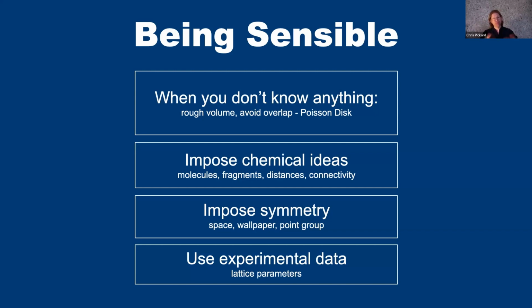Now that's sort of physics. But beyond that, you can also make the structures sensible from a chemical point of view, so that atoms are combined in fragments or into molecules, and the distances between the atoms are chemically sensible distances as well. So you can use this as a pre-filter for your random structures to just sample the ones that are likely to be low energy. Now, this is biasing the sample in some sense, or you can think of it as restricting it to a region in configuration space. And if the solution that you're interested in lies somewhere else outside of these constraints that you had applied, you'll miss it. Okay, but that's the art.